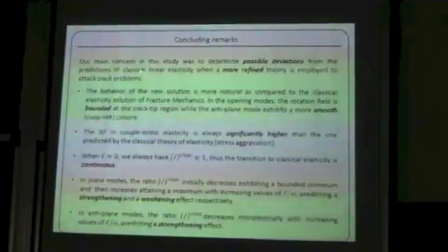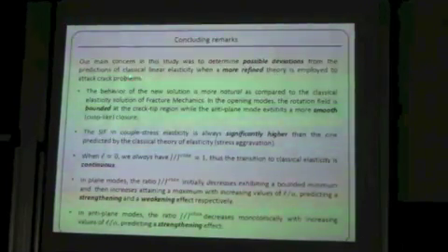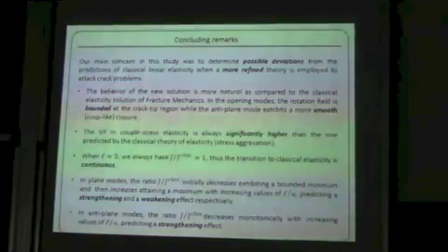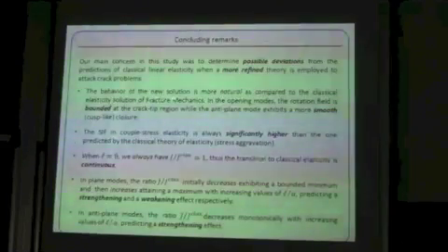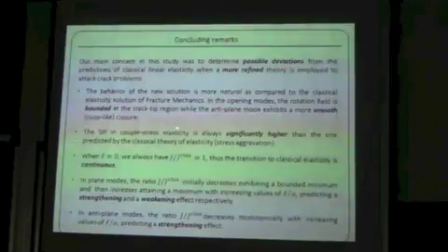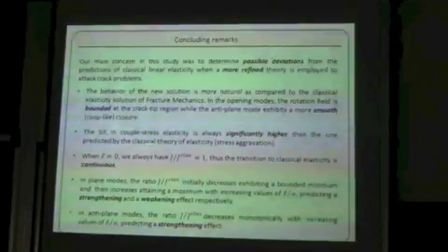So some concluding remarks. The main concern in this study was to determine possible deviations from the prediction of classical linear elasticity when a more refined theory is employed for crack problems. In several cases we observed a more natural behavior with bounded results and smoother crack closures. We also note that the stress intensity factor in this theory is always significantly higher, and also we have observed